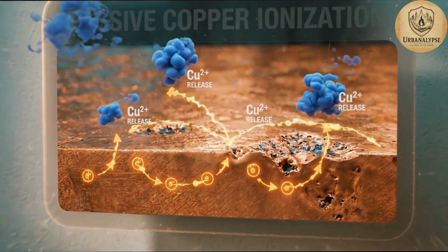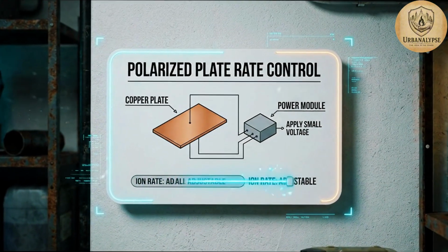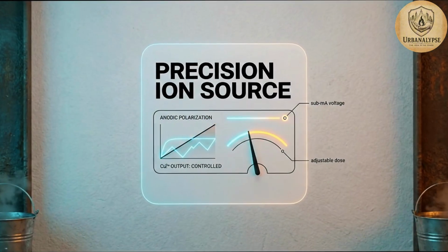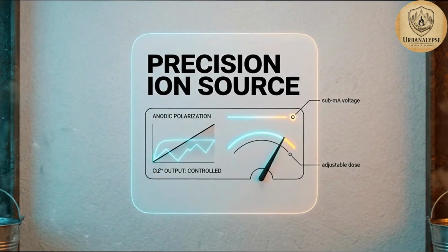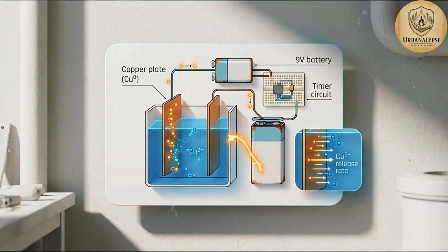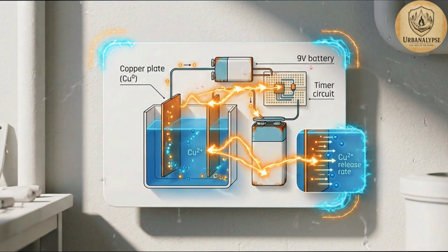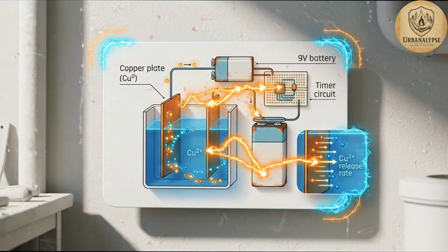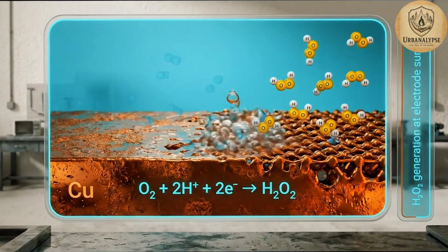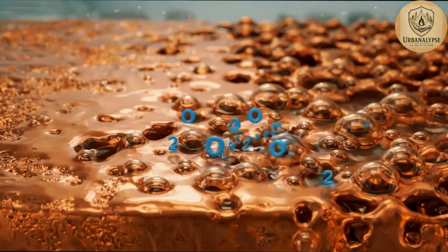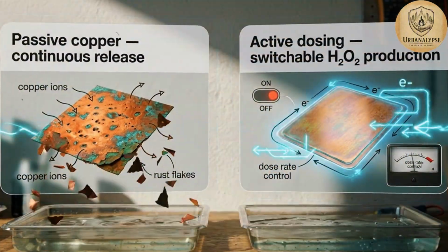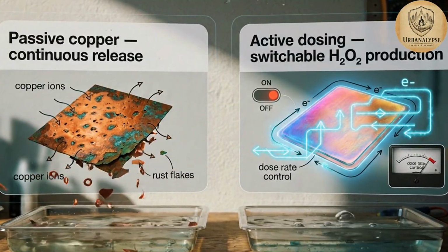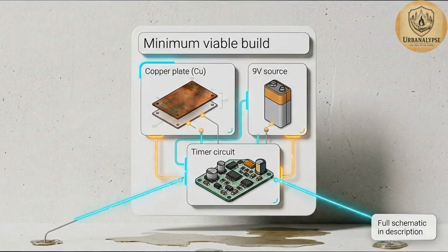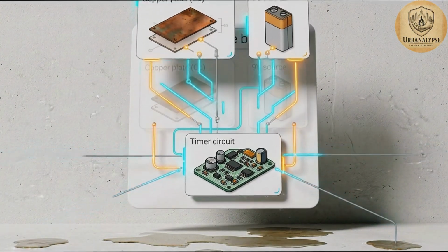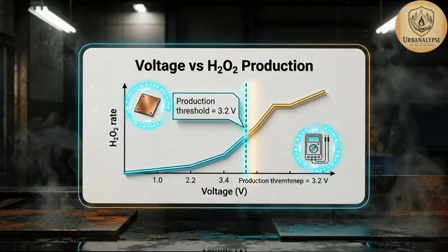Electrochemical copper electrodes. Passive copper ionizes at whatever rate the water chemistry allows. A polarized plate lets you set the rate. Apply a small voltage to a copper electrode submerged in water, and you're running a precision ion source. Anodic polarization releases Cu2+ at a controlled, adjustable rate. At specific voltage ranges, the same electrode also generates hydrogen peroxide directly at the metal surface, a secondary oxidant produced in situ with no chemical input. Minimum viable build: copper plate, 9-volt power source, timer circuit. Full schematic in the description, including voltage thresholds for H2O2 generation onset.